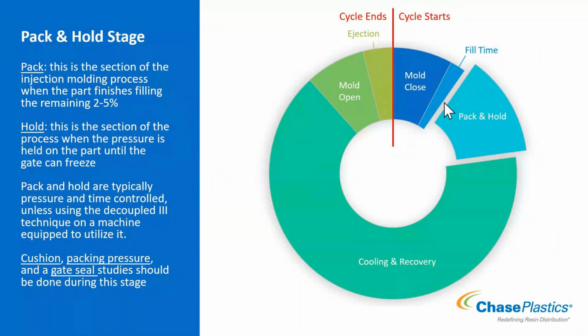So now that we've talked about triggering pack and hold, let's get into that just a little bit. So pack, this is the second stage of the molding process when the part finishes filling that remaining 2 to 5%. We still need to put volume into the cavity during the pack phase, not only to account for the change in density through solidification, but also note that we are injecting to 95 to 98% under fill, so we have to take up that other 2 to 5% under pack, and then a little bit more to account for that densification during solidification.